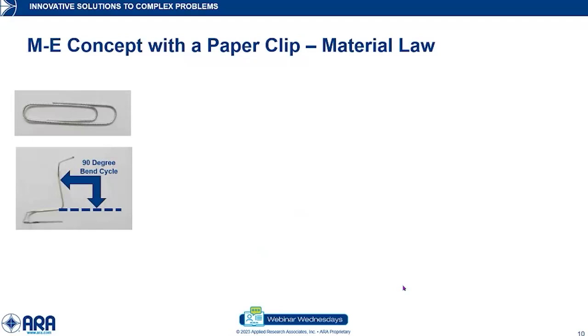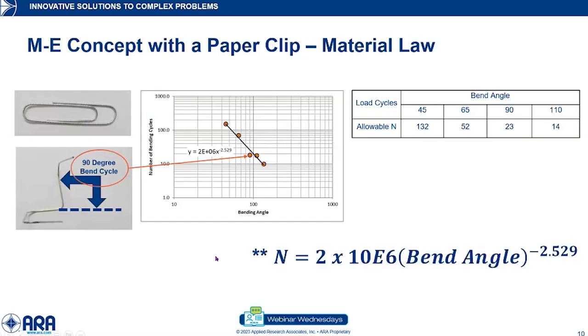these concepts that we're going to go over with just a simple paperclip. So what we're trying to do here is find out how many times we can bend the end of the paperclip at a 90-degree angle, bend it back, and keep going through those cycles. How many times can we do it before it actually snaps off? So experimentally, we're going to try this at different angles. You can see the data point. So bending it at 90 degrees, we can go a total of 23 times, 65 degrees, a total of